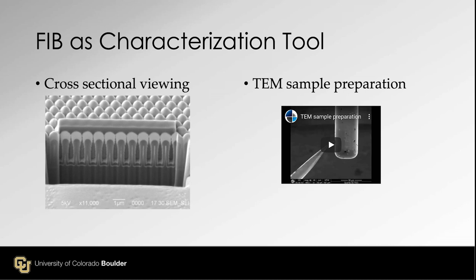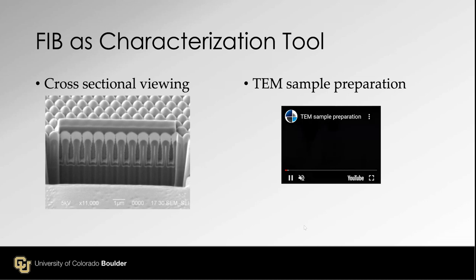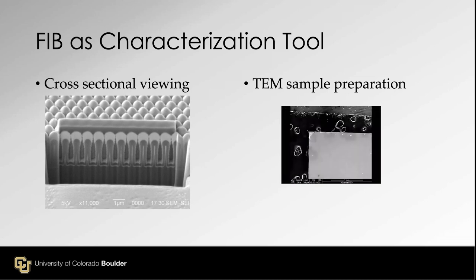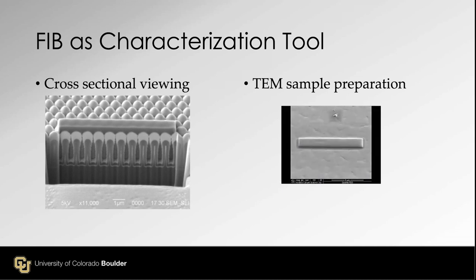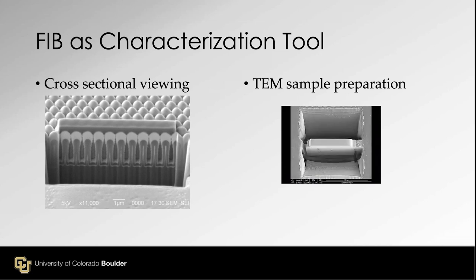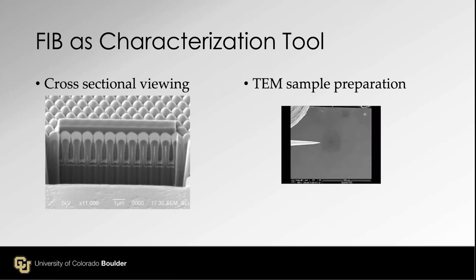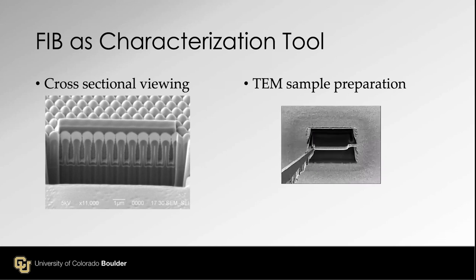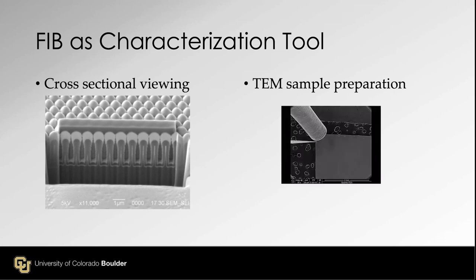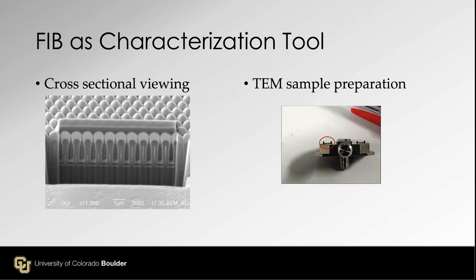From the top, you see something like those spherical things, arrays there, but you can check what's going on underneath. And also the TEM sample preparation. So inside the FIB chamber, first you wanna put platinum in the area you wanna cut off the slab, okay? So you remove the material from four sides. Now you bring in the Omniprobe micromanipulator, attach the tip to the slab and remove it. You have a 10 micrometer by 5 micrometer slab.